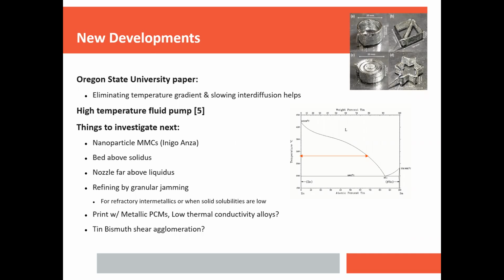Does anyone else have any other questions? Yeah, I have one other question. You're not doing this in a vacuum, correct? Or have you tried that? So yeah, processing under inert atmosphere and vacuum definitely enable higher temperature printing. So like if you want to do steel, you're definitely not doing that in air. The oxide formation is way too fast for good interlayer adhesion. But yeah, under vacuum, under reducing atmosphere as well is interesting. As long as there's no hydrogen embrittlement, that really depends on the alloy. I have the equipment to try that. It just adds additional complexity, and tin alloys oxidize so slowly that it's hardly an issue for those.